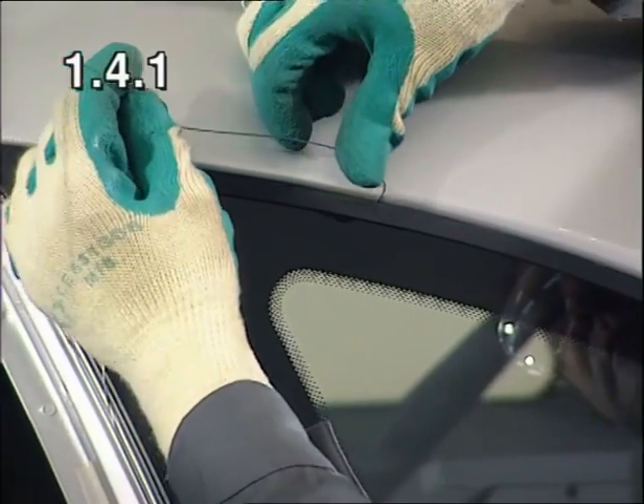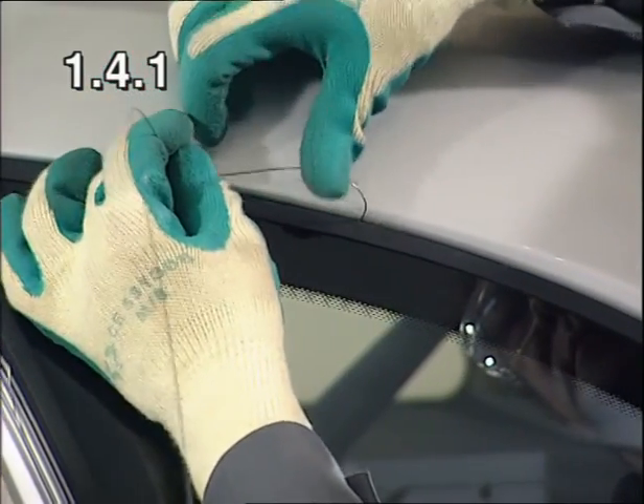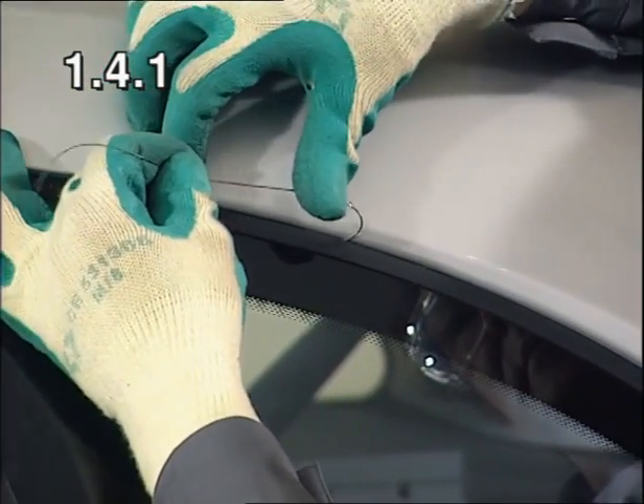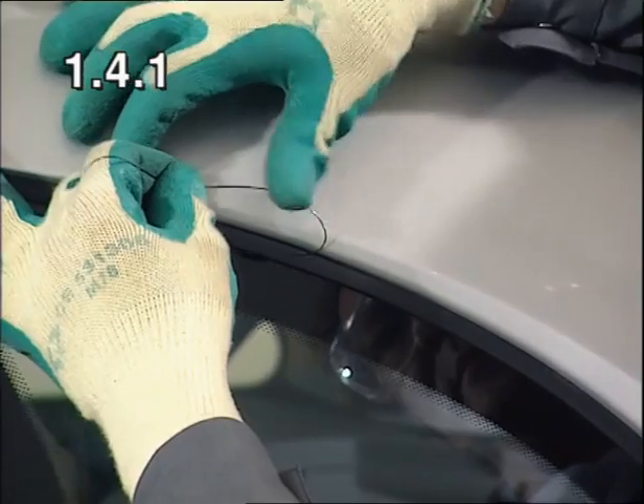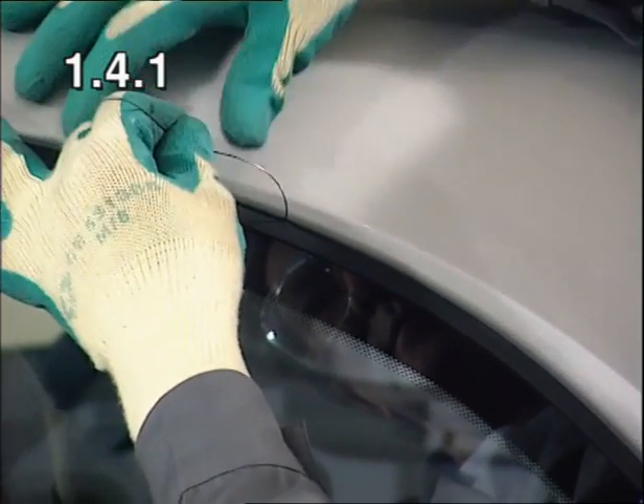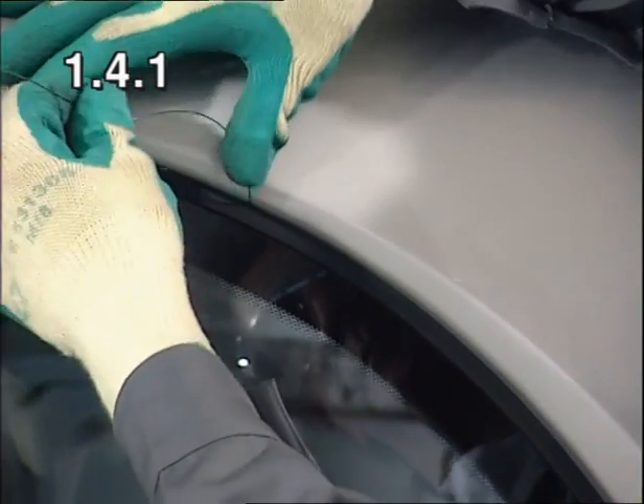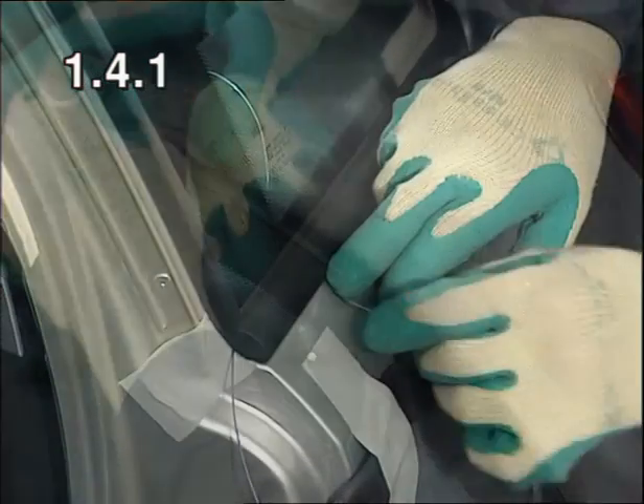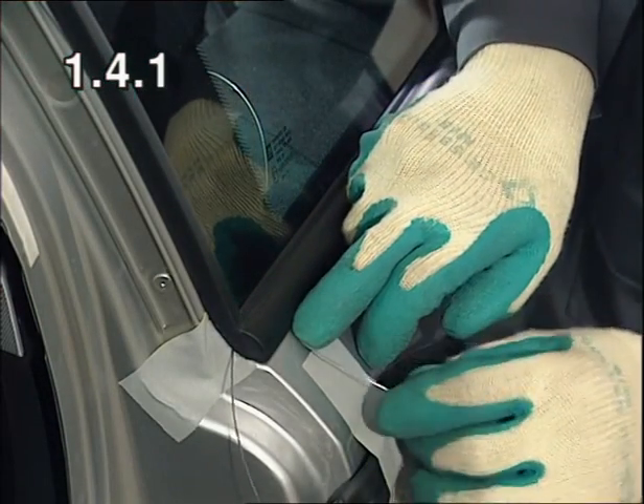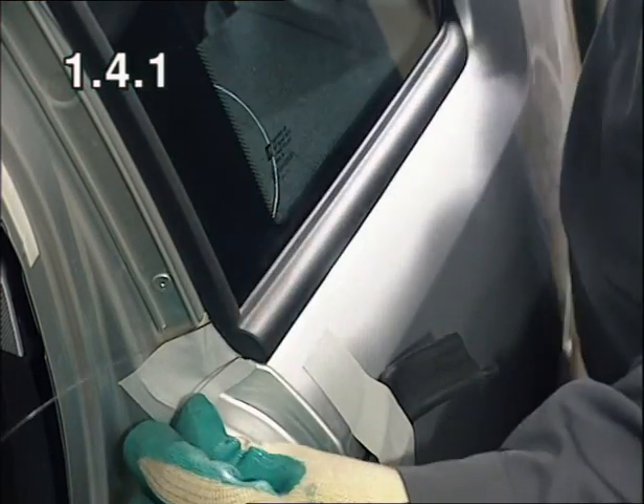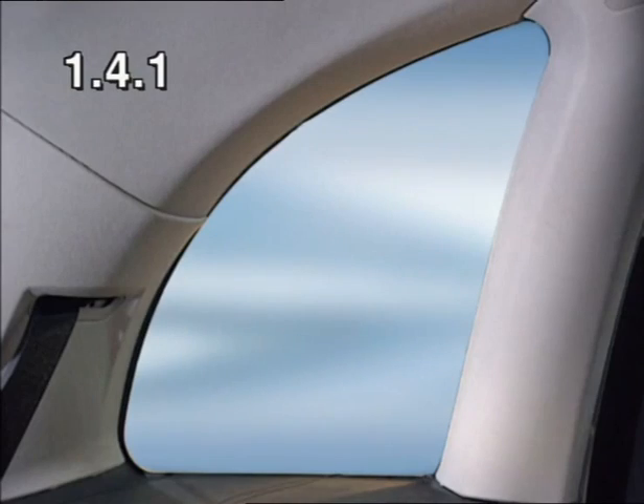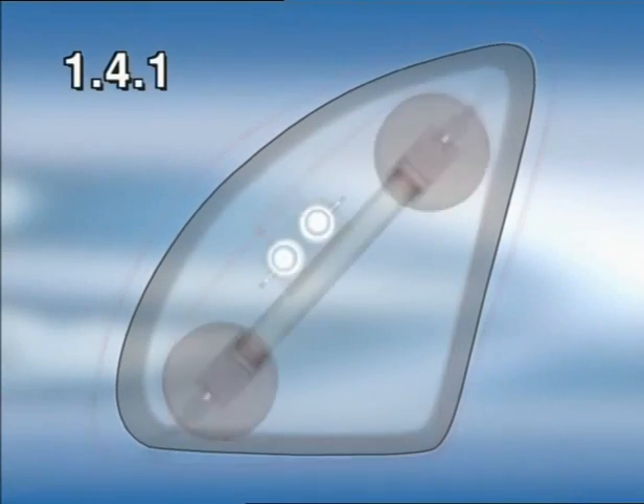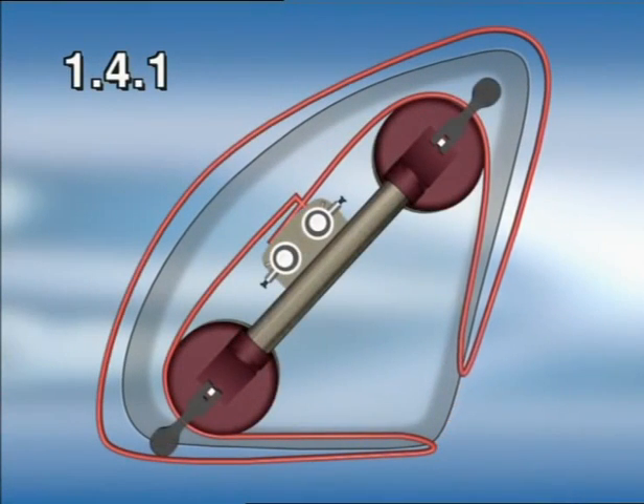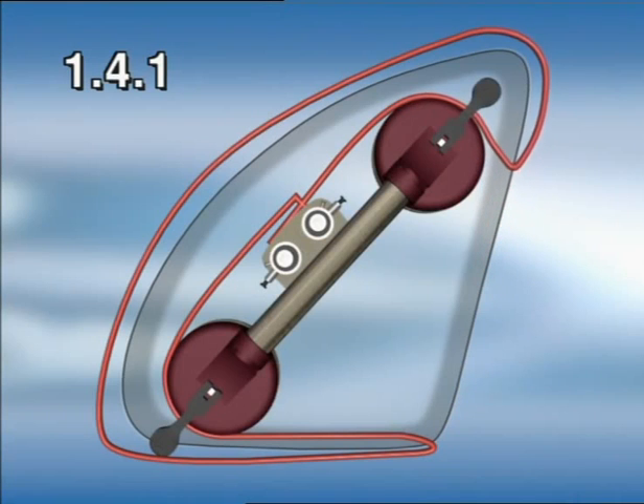To enable the wire to be rolled in more easily under the window, spray some washing up liquid diluted with water onto the flexible seal. Never use silicone or spray oils. These substances can penetrate the adhesive during cutting and result in loss of adhesion when the window is reinstalled. The quarter panel window is removed with the double reel in 2 stages.